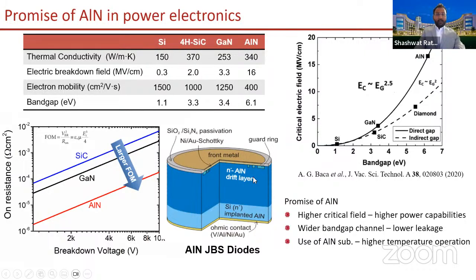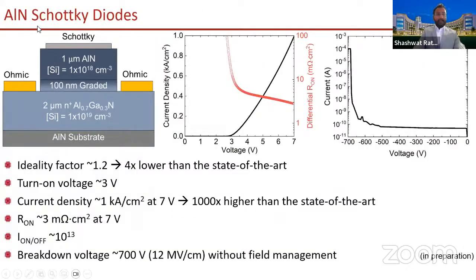So I feel that aluminum nitride technology has a long way to go because of the complications in doping this material, but we have had exciting results on this front. In the interest of time, I would not be showing those results, but yes, we have been able to dope these materials reliably now, and these materials are no longer insulators, but can actually be used as semiconductors. For example, we developed these aluminum nitride power diodes.